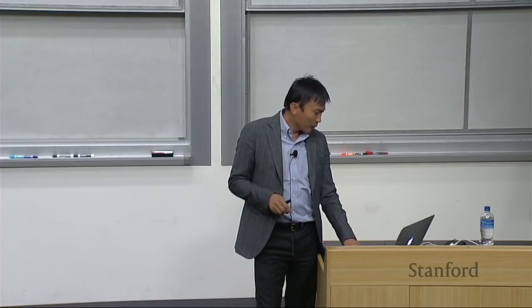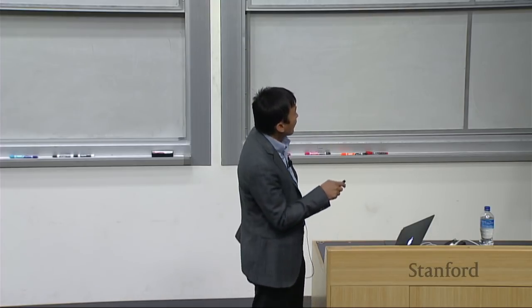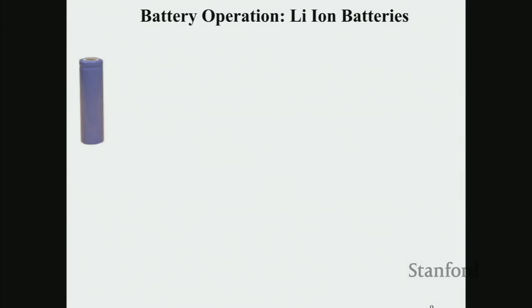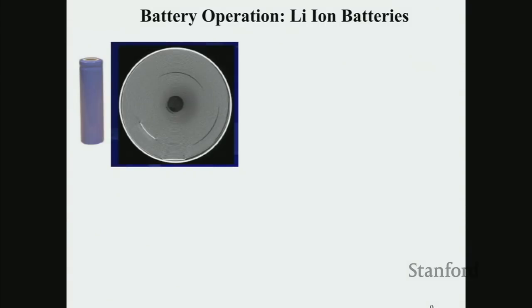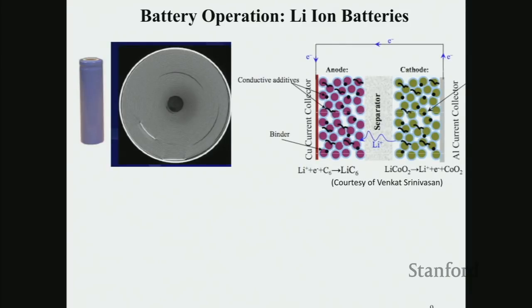Well, if you look at how the batteries work, let's come to battery 101. You take a cylinder cell, that's in the Tesla car. You cut it open. It has this jelly roll. If you zoom in and look at this, you have copper foil, aluminum foil. Now people try to push the limit. In the copper foil, 5 micron, 7 micron, aluminum foil, less than 10 micron. And this is the battery separator, right? They're separating anode and cathode. Anode consists of these particles, as well as cathode. They can store lithium in their crystal structure.